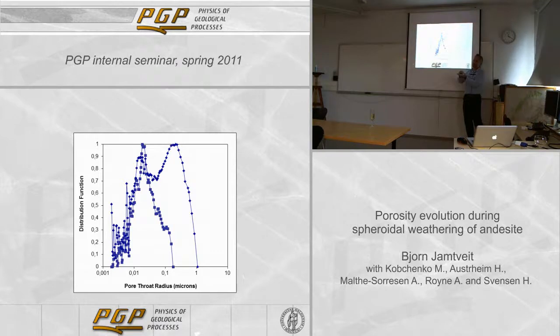The aperture can be pretty small, so that the opening of the pore is relatively small compared to the pore throat. So we think this peak here is related to microscopic fracturing in the rock. It doesn't form big pores, but it forms fractures with big throats compared to the size of the pore.